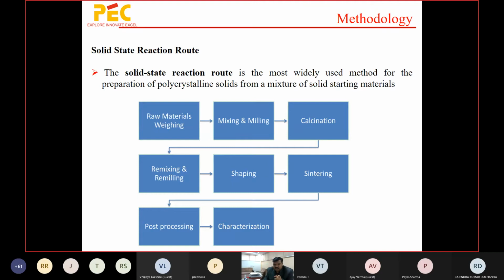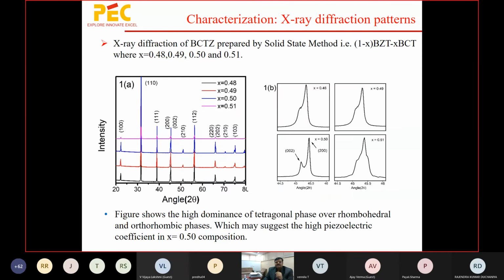After mixing, milling and calcination, we can take the XRD, X-ray diffraction pattern, so that we can judge the crystal structure. After sintering, again we can take some part of the pellet and do the XRD to confirm the crystal structure. In this case, we took four compositions, 0.48, 0.49, 0.5 and 0.51 for BCTZ. And these are the X-ray diffraction patterns. Very good X-ray diffraction patterns we have observed here.